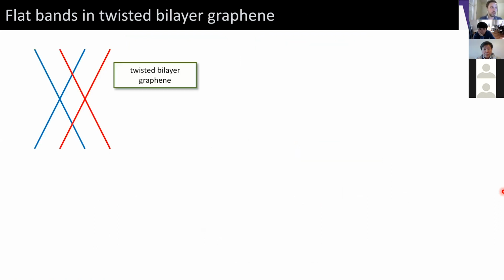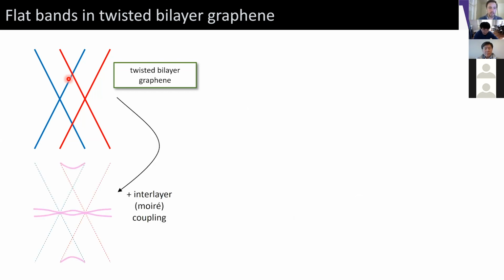Now, it's helpful to think about what's happening to the bands of twisted bilayer graphene a little bit less schematically. So we can imagine that when we have two rotated graphene sheets, in momentum space, we have these two Dirac cones, which are slightly offset due to the twist angle. And now if we turn on an interlayer coupling term between these two graphene layers, these crossing points at the center of the Moiré-Brillouin zone become avoided crossings and they gap out. And so these low energy bands end up getting flattened towards zero energy.